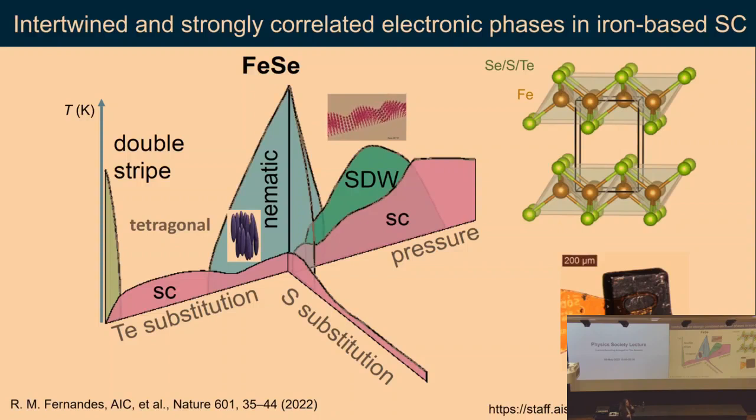Superconductors in general do not like strong magnets because the superconductivity is destroyed. So it was not at all predicted that this could occur, and it seems like it's possible, and it's not just these materials, but there is a huge family of different combinations of elements while still maintaining these two-dimensional planes of iron. So once you have this iron layer coordinated in the tetrahedral environment, you create superconductivity for different